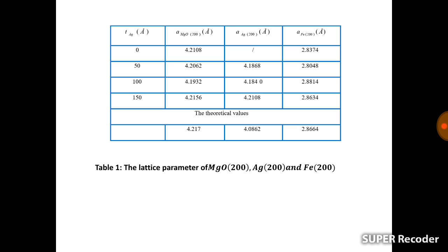Thus, it is obvious that the lattice parameters of the silver buffer layer are higher than the theoretical values, indicating that this layer is in a state of compressive stress. The lattice is dilated, explained by the mismatch between this layer and the substrate. Moreover, it is clearly seen that the lattice parameter of the magnetic iron layer is lower than the theoretical values, which shows that the iron layer is in a state of contraction.